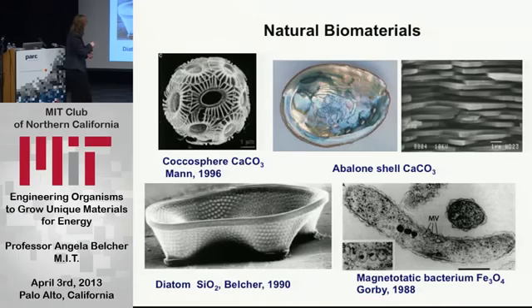And this has actually been a big inspiration for our group for lots of different kinds of materials, anywhere from trying to target cancer cells to enhance oil recovery. This beautiful organic inorganic structure. This is the abalone shell again, and if you fracture this and you look at it in scanning electron microscopy, what you see, this is a 1 micron scale bar, is that it's made out of these plates, these stack of coin plates, and they stack on top of each other. But they don't stack on top of each other just in these columns. They actually interdigitate and they overlap, and it's this structure that actually helps give it its very tough structure. And in between each individual tablet is an organic matrix. It's coded by the DNA that actually nucleates, controls the structure of this inorganic material.